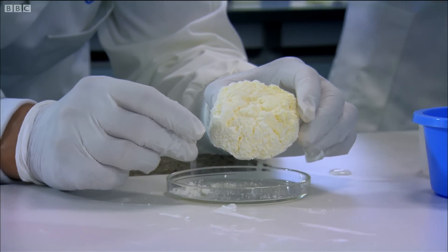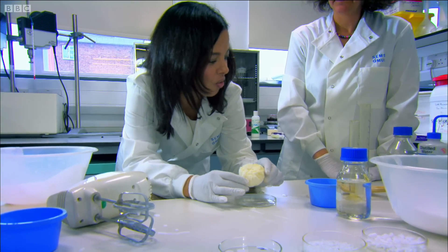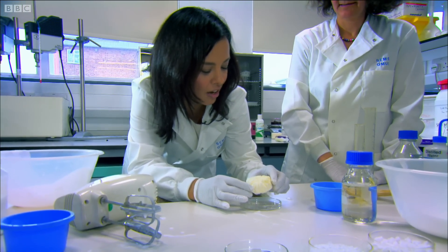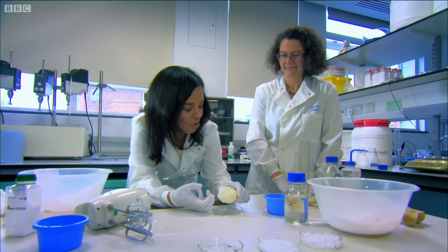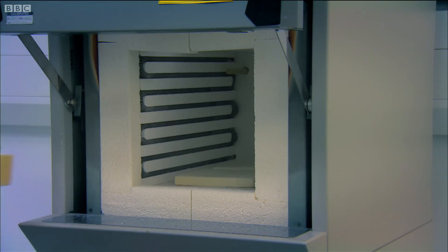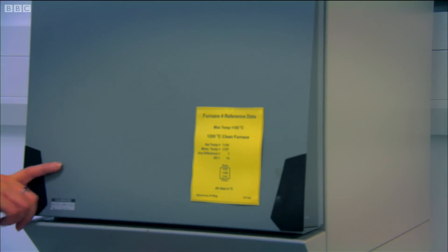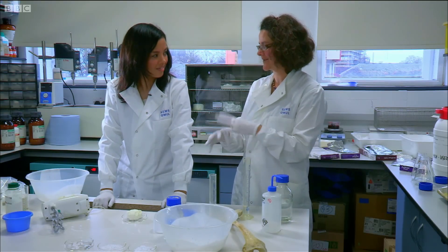This now represents a very bone-like graft that you can place in a fracture to allow the natural healing process to occur. The next thing we have to do is fire it just like you fire a ceramic pot. The ceramic particles will fuse together as the temperature gets hotter, and that gives it its nice solid structural integrity. But because of the way the PVA has foamed it, you've still got that macrostructure and microstructure — that porosity needed for it to work as a bone graft.